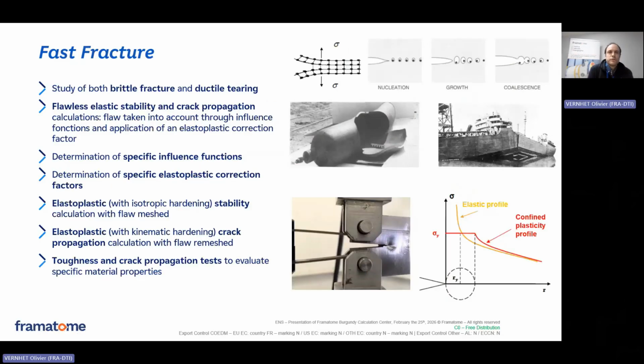The last failure mode that I want to speak about is fast fracture. Of course, when we study fast fracture, we study both brittle fracture and ductile tearing. Once again, we begin with quite basic calculations, flawless elastic stability and crack propagation calculations. So we don't model the flaws. We use only an elastic mechanical behavior of our equipment. We use, to model the flaw, some influence functions that are codified and implemented in our post-processor.